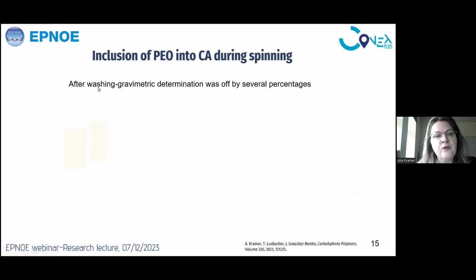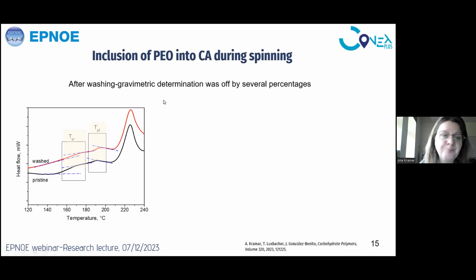We also saw that after washing, in gravimetric determination, we were measuring the weight of our nonwoven material before and after washing. We saw in the polyethylene oxide DSC, differential scanning calorimetry, that we don't have the melting temperature of polyethylene oxide, and this gravimetric determination was off by several percent. We constantly get the weight of our material after washing and drying that should contain some small amount of polyethylene oxide, but we couldn't see the exact melting peak of polyethylene oxide on DSC.